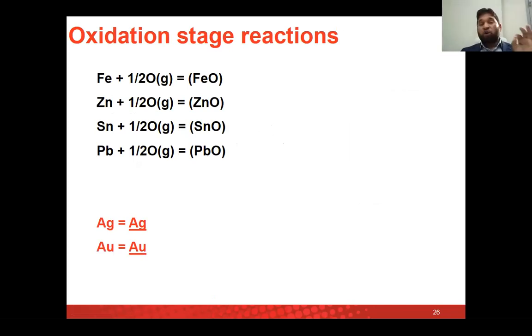After the reduction stage, the next stage is the oxidation stage. What we do in the oxidation stage: we have this iron, zinc, tin, and lead. All of these are now impurities in black copper. Now we need to remove these impurities from black copper to increase the purity of copper. So we do the oxidation of this one. We inject some hydrocarbons, we inject oxygen, and we do the oxidation steps. Iron becomes iron oxide and goes into slag. Zinc reacts with oxygen, becomes zinc oxide, and also goes into slag. Tin goes to slag, and similarly lead will also go into slag. But the gold and silver that we started with will still remain in the copper.